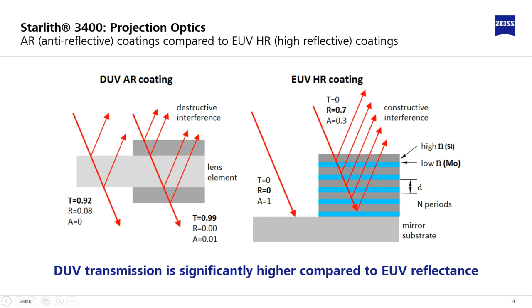Only if the substrate is coated with a multilayer coating, consisting of alternating layers having high and low index refraction, a considerable part of the incoming light is reflected. This time by constructive interference.